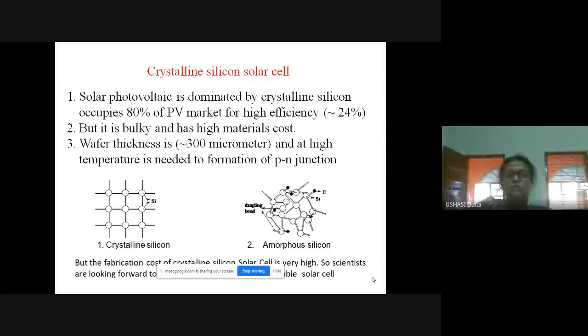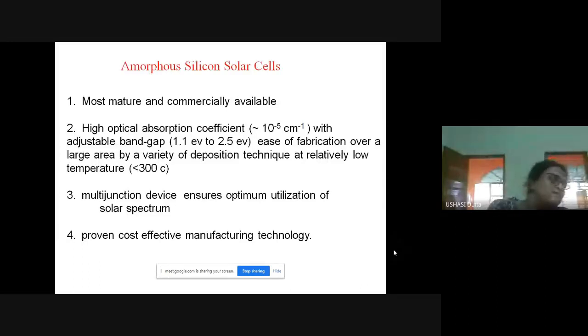Because of the fabrication cost of crystalline silicon solar cell, the scientists are looking forward to amorphous silicon solar cell. The amorphous silicon solar cell is produced generally by thin film technology, and this is the most mature and commercially available material, with an optical absorption coefficient of the order of 10 to the power minus 5 centimeter inverse with an adjustable band gap. It is very easy to fabricate over a large area, the deposition technique is very simple, and the multi-junction device ensures the optimum utilization of the solar spectrum, and it is also a cost-effective manufacturing technology.